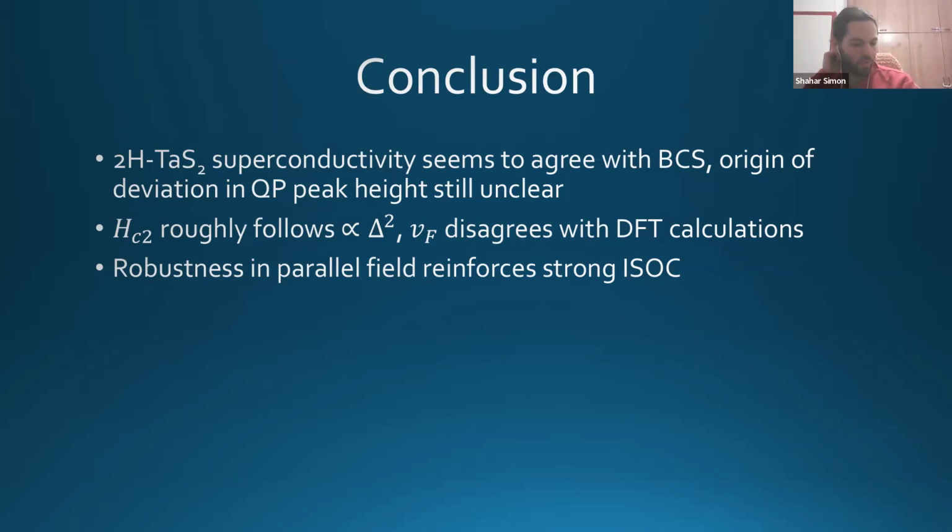No, actually, there are a few hypotheses by different people. Some groups theorize that maybe there's a second gap that opens when you thin it down. We don't see evidence of that. There was a group that hypothesized that there may be an interplay with the charge density wave, that when you go to thinner samples, the charge density wave signal seems to diminish, and then it frees up density of states to go into the superconducting state.